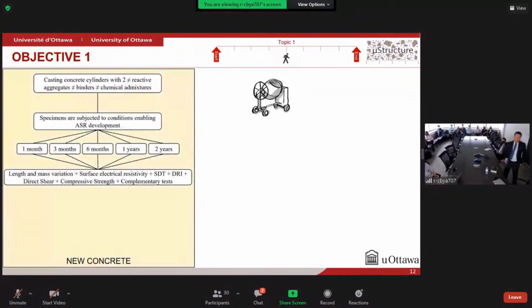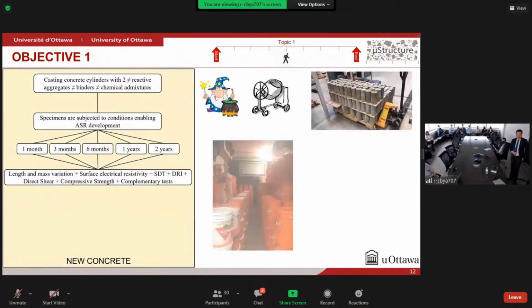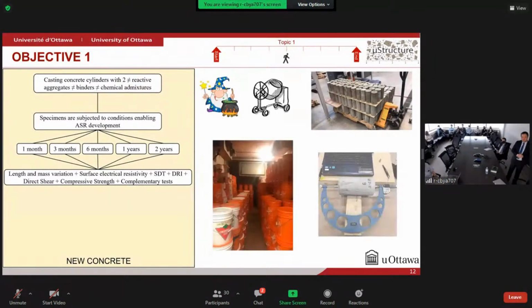So in the first objective of this research, we are going to be casting different concrete cylinders with 2 different reactive aggregates, different binder materials, and different chemical admixtures. The chemical admixtures here are the self-healing agents. After casting, we're going to be subjecting the specimens to the development of ASR, and over time, we are going to be measuring them mechanically and microscopically.